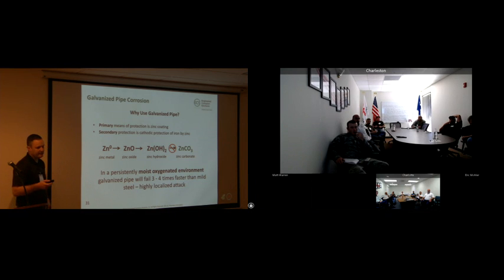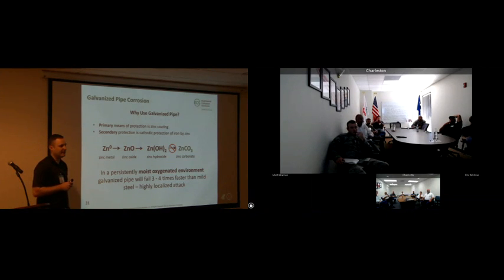Well, when we talked about how we make galvanized metal earlier, we talked about a chemical reaction that has to happen. And what that is, we put the zinc onto the iron, onto the steel. We get that, it absorbs some oxygen out of the atmosphere, forms a zinc oxide. Get that zinc oxide wet, it forms a zinc hydroxide. We let that zinc hydroxide dry out, forms a zinc carbonate, and we've got galvanized metal.